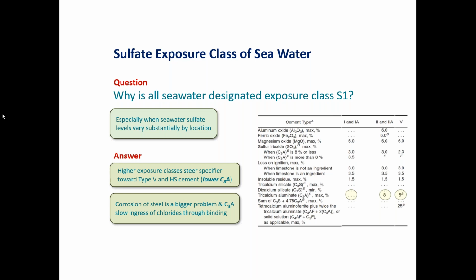So when it comes down to it, the C3A isn't all that bad. When it comes to chlorides, the C3A hydration product actually binds chlorides. So you have these big structures, let's say bridges and other types of structures exposed to seawater. The C3A component is actually helping to bind up the chlorides, picking them off as they're intruding into the concrete, and helping to prolong the period of time before the chlorides can get to the reinforcing steel and interact with it. And obviously, once that starts to happen, it's big time trouble. So that's the explanation as to why seawater is sulfate class 1.